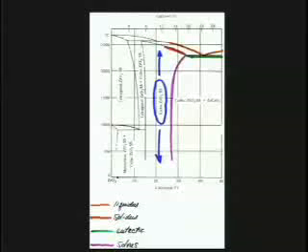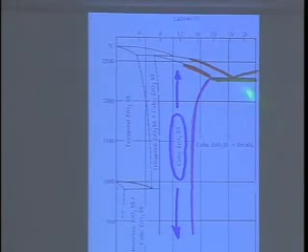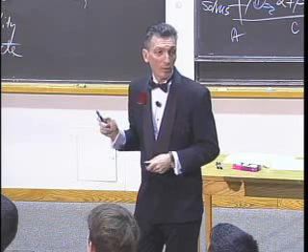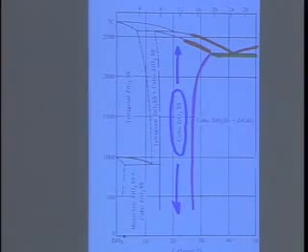Here's zirconia. Remember, zirconia at room temperature is monoclinic, and that's no good, and cubic zirconia is stable only at very high temperatures. But look at this. If we add calcium oxide to zirconia, we have this huge range. It's a eutectic system. There's the eutectic. But en route, we stabilize the cubic form all the way down to room temperature. So you're buying a stabilized zirconia, meaning that the cubic form has been stabilized. And that's the one that's got the high refractive index.